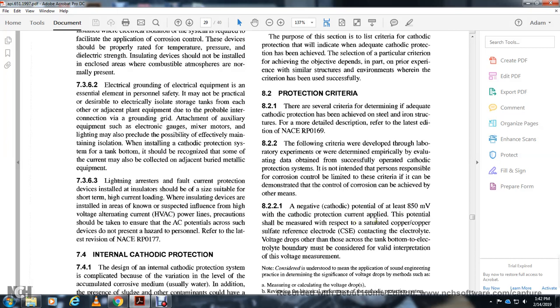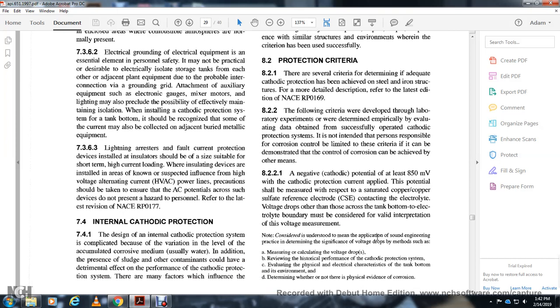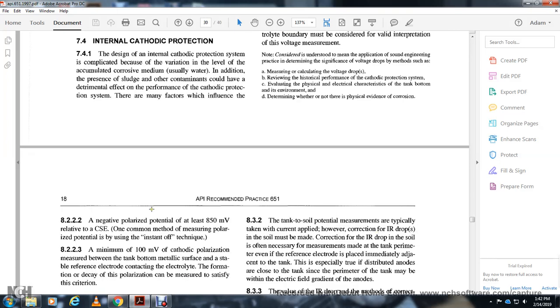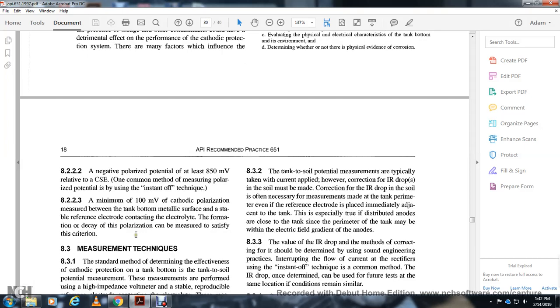The potential should be measured with respect to a saturated copper/copper sulfate reference electrode, with attention to the voltage drop other than across the tank bottom to the electrolyte boundary. It must be designed for valid interpretation of the voltage measurements. A negative polarized potential of at least 850 millivolts with respect to the CSE, and a common method of measuring polarization potential is the instant off technique.